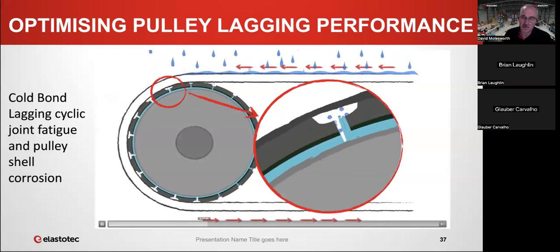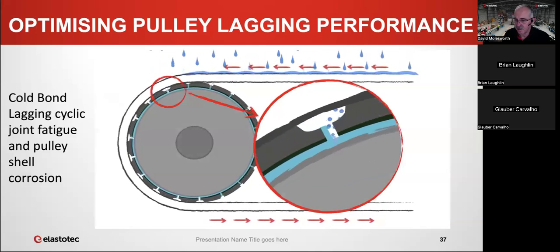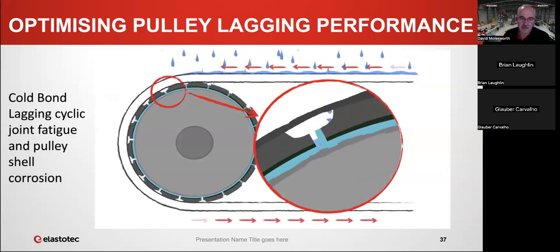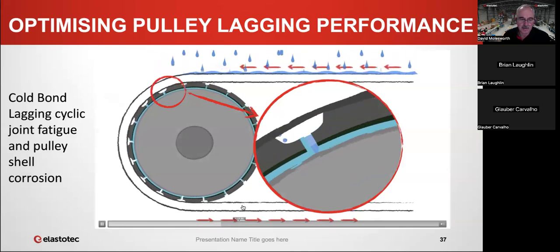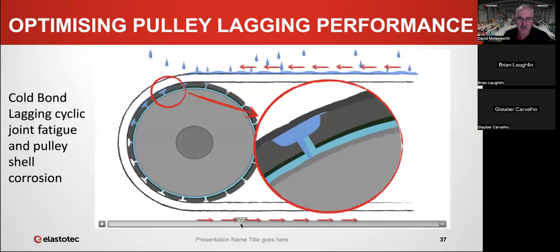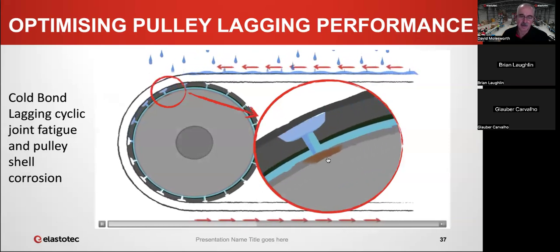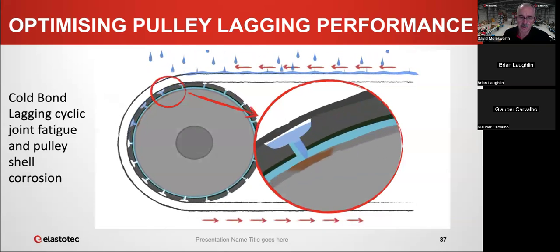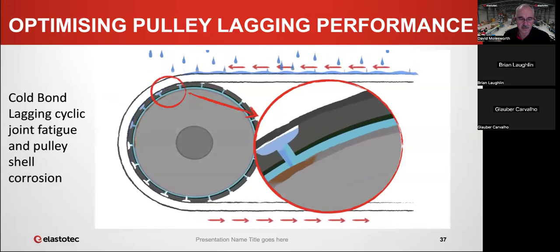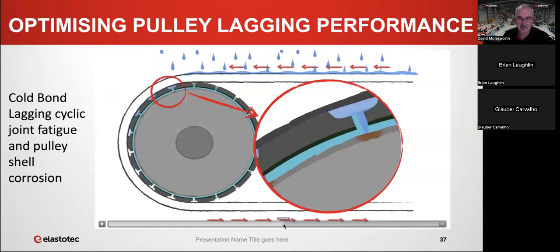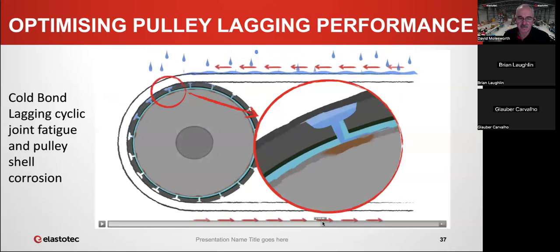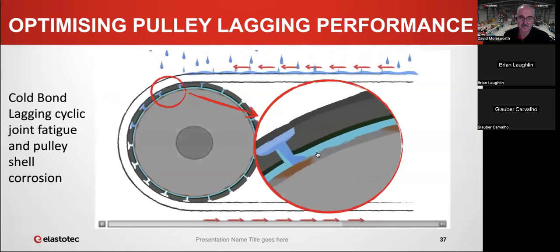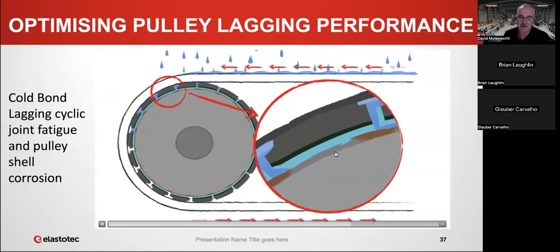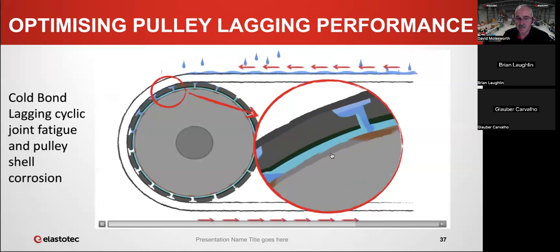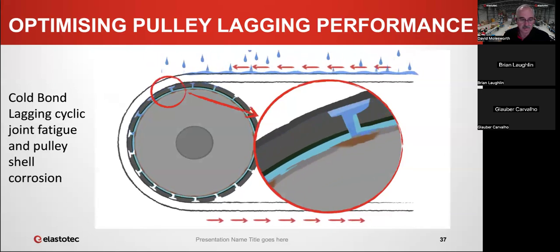And then, of course, if there's moisture, if the conveyor is operating in wet conditions, it rains, etc., that moisture will find its way through that weak point and it'll come down to the shell. And what starts to happen then is you get corrosion of the surface of the shell, and eventually that corrosion will lead to debonding. Basically, the lagging starts to lift away from the shell, and the corrosion starts to eat into the pulley shell.